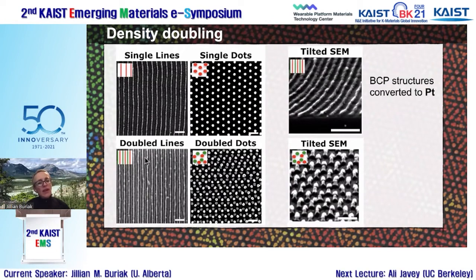Now, there's one little caveat. You can see that the single lines, so these are all 100 nanometer scale bars, the fidelity is not perfect. And so the single lines are all bright, but when we double it, you can see that it kind of goes bright, dim, bright, dim. You see this alternating pattern. It's like, what's that due to? And I'll explain that in a second.